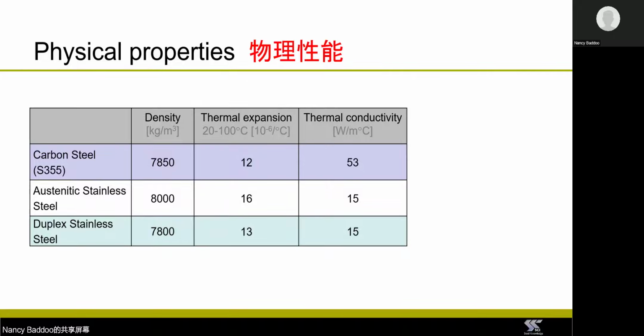So this is good, and it can also be bad. It's good because materials with low thermal conductivity prevent the transfer of heat. So this can help in achieving enhanced energy efficiency, and stainless steels are sometimes used in thermal block type components for this reason. When it's bad is when you're welding and you want the heat to dissipate, and it doesn't dissipate so quickly because of the low thermal conductivity. So there are special procedures that give guidance on welding to minimize distortion, which might occur because of the lower thermal conductivity.